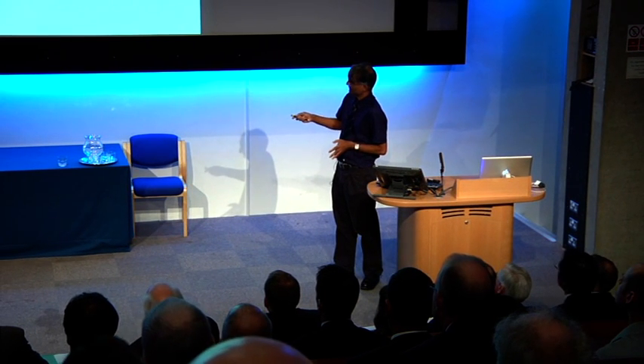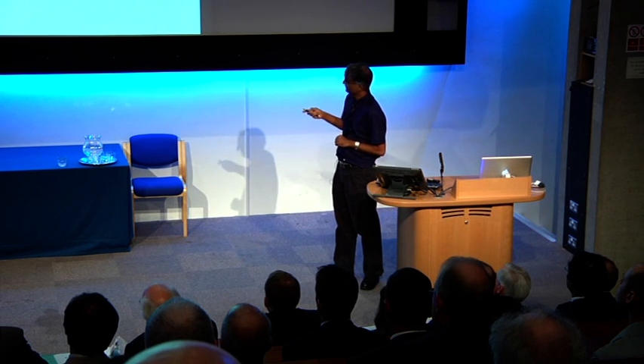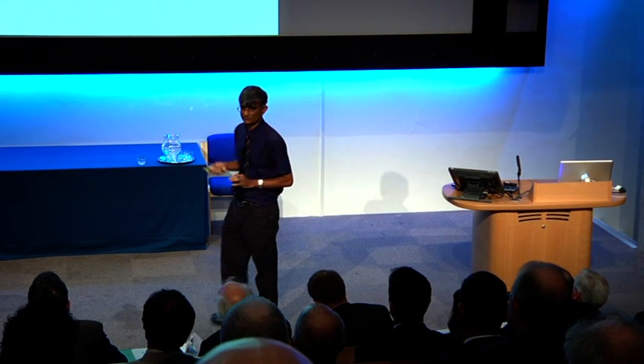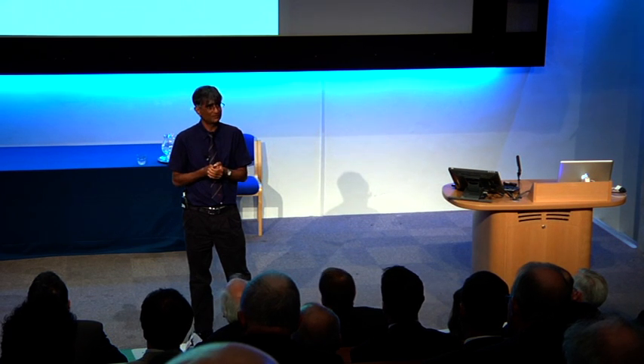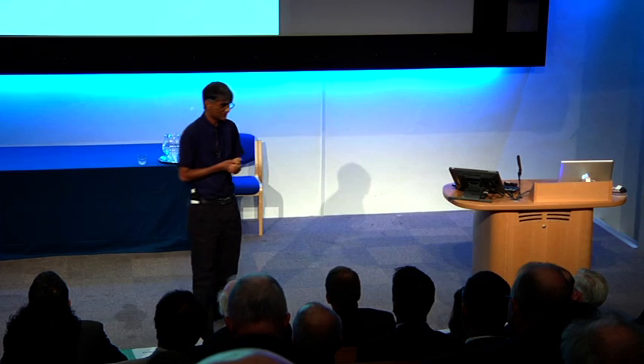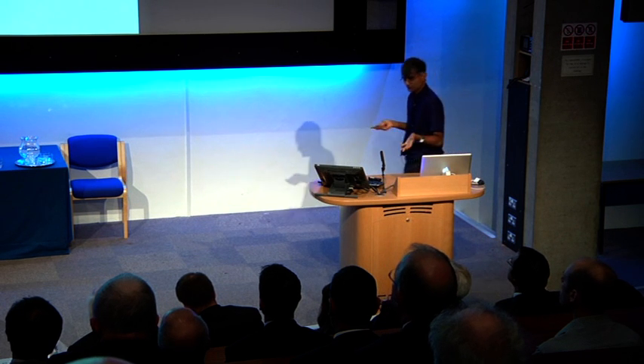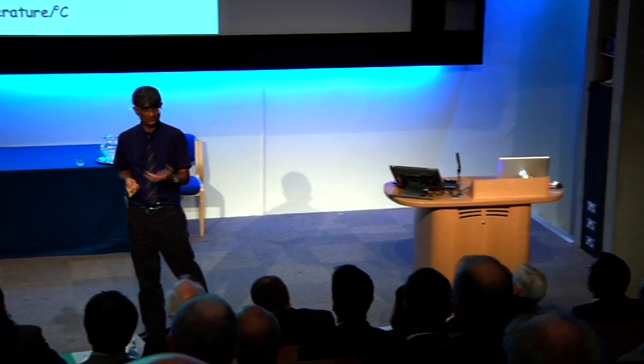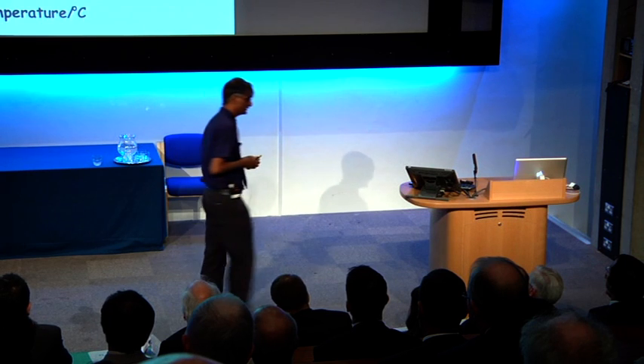So we designed a steel completely theoretically. This is carbon, this is silicon to stop the cementite, and the other elements are needed in order to stop other transformations from interfering. And I'll come back to this particular element later on, because we can't purify steel sufficiently to kill the phosphorus. So we've got to add another element which getters the phosphorus, which stops it from doing harm at austenite grain boundaries. It has a beautifully simple structure with just two phases, both of which are not in themselves hard. So austenite is not particularly strong, and ferrite is not particularly strong. But if you have an intimate mixture, then that can be very strong.